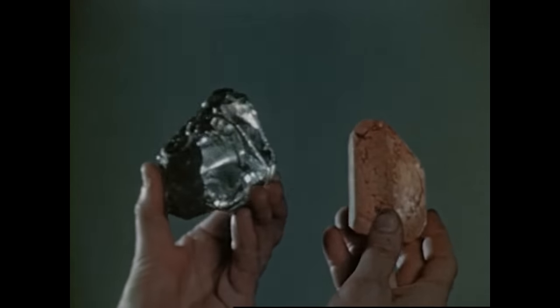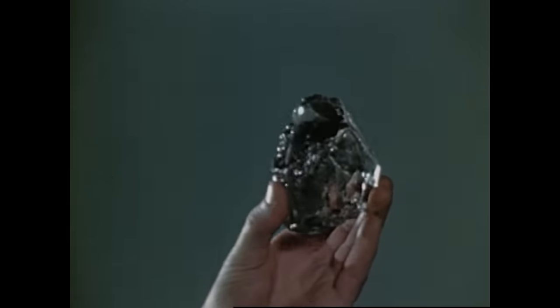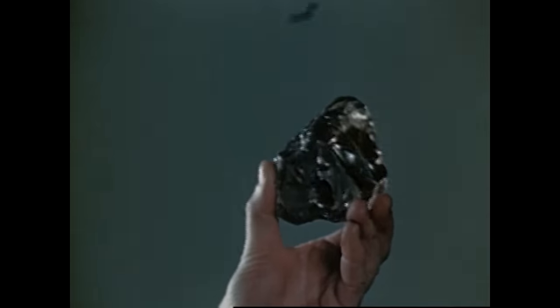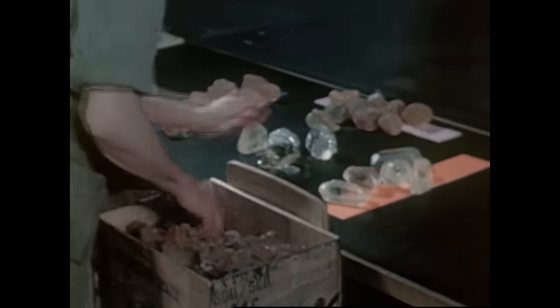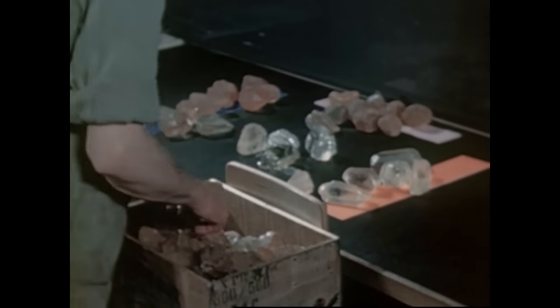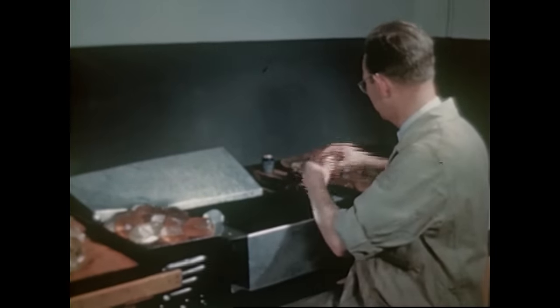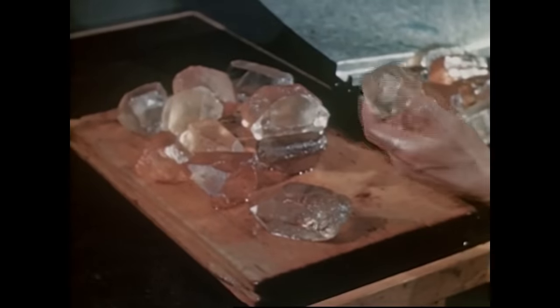Sometimes quartz has a reddish appearance on the surface, and occasionally it is a smoky color throughout. But color is of little importance in making radio plates. After preliminary sorting, there is a thorough inspection for cracks, optical twinning, inclusions, and other internal imperfections. This is done in an immersion tank filled with a special type of mineral oil.